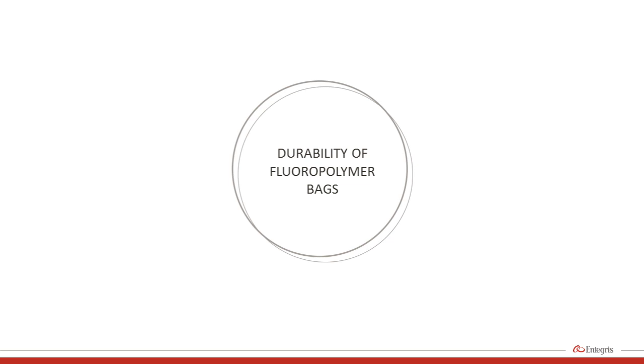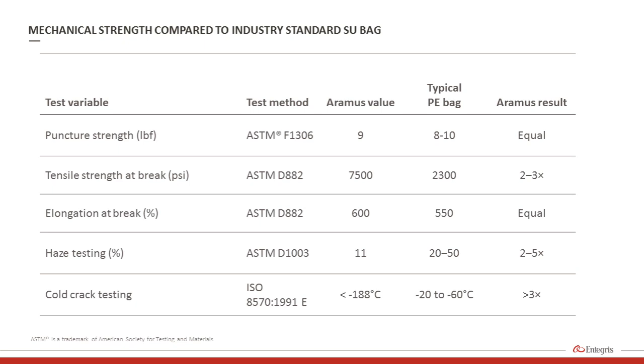Next, let's take a look at material durability. The mechanical data in this table shows that fluoropolymer product is as good or better than a multi-layer polyethylene bag. In terms of puncture strength, they're about equal. Tensile strength at break, the fluoropolymer film is 2 to 3 times better. Elongation at break, they're about equal. And haze testing, the Aramus film is 2 to 5 times more clear than a multi-layer PE bag.